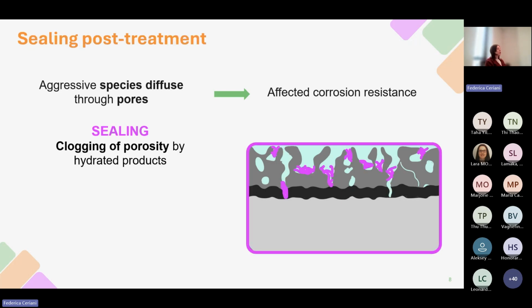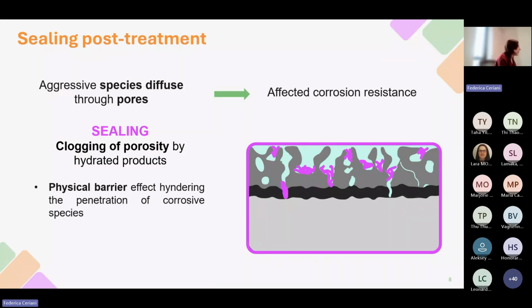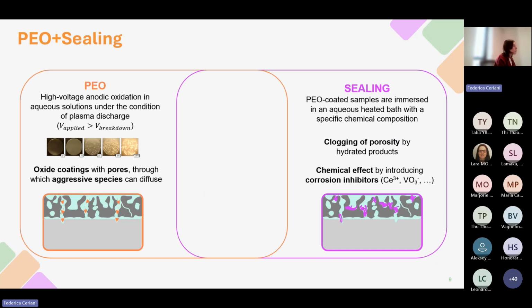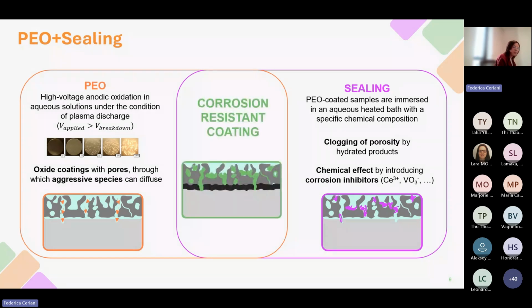To solve this problem, it is possible to perform a sealing post-treatment with the aim of clogging the porosity of the PEO coating by precipitation of hydrated species. So a sealing post-treatment provides a physical barrier effect, which allows us to enhance the protective behavior of a PEO coating. This physical protective effect could be combined with a chemical effect simply by introducing corrosion inhibitors within the sealing bath. Such inhibitors remain contained within the sealed PEO coating and could be released in case of corrosion. So by combining a PEO treatment with a sealing post-treatment, it is possible to produce corrosion-resistant coatings.